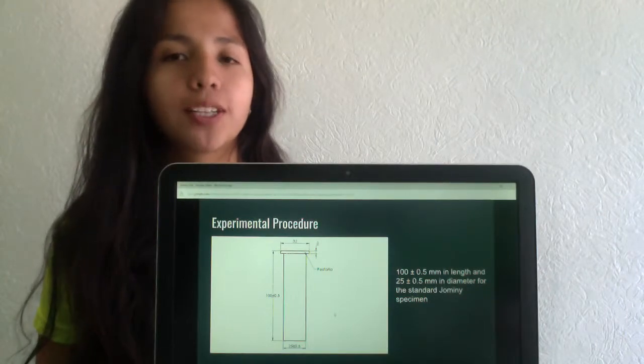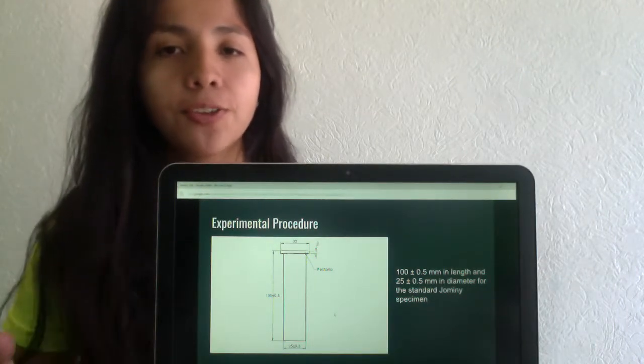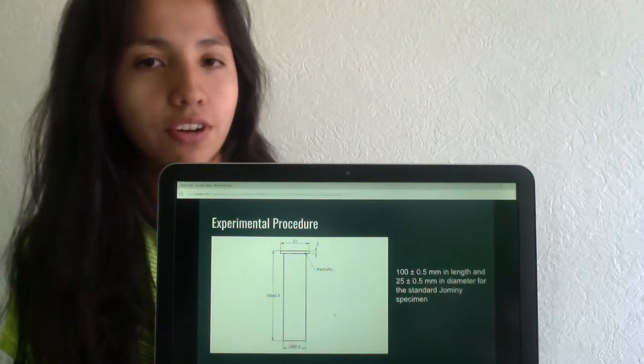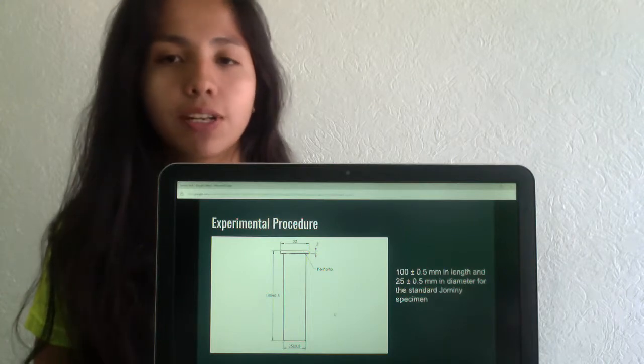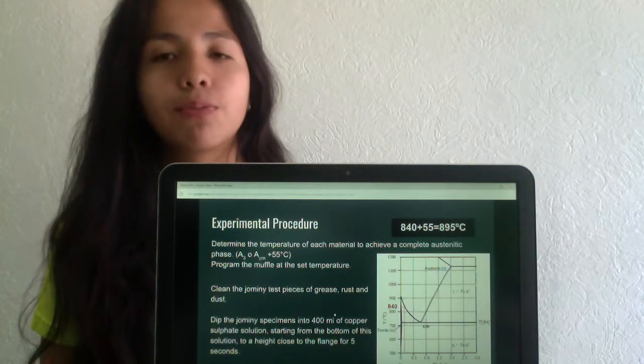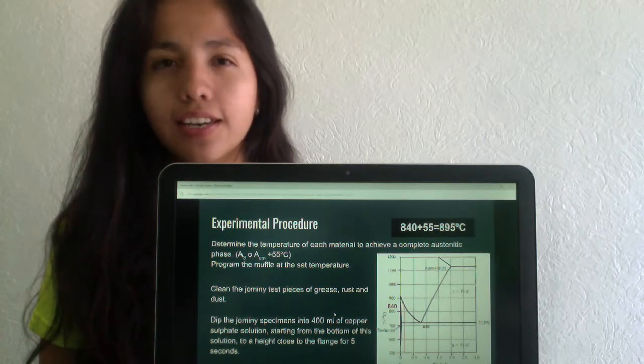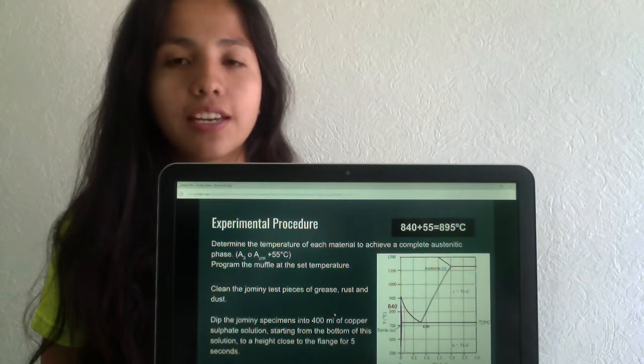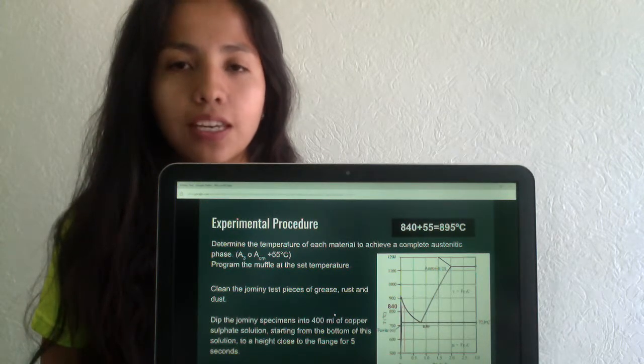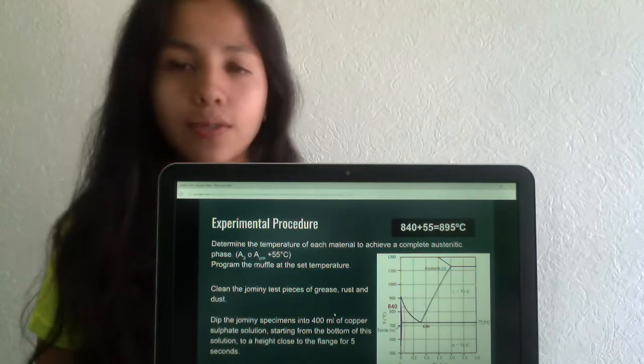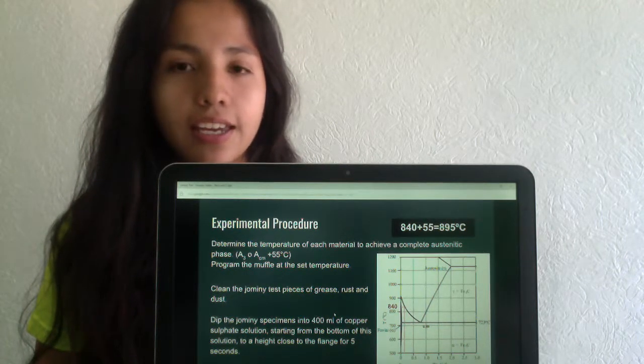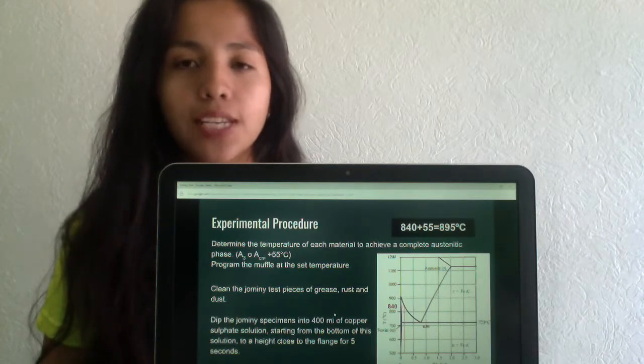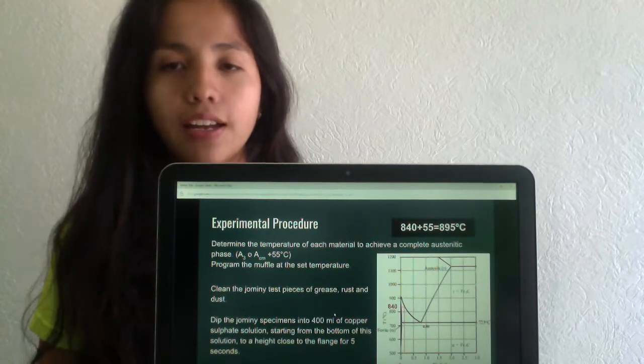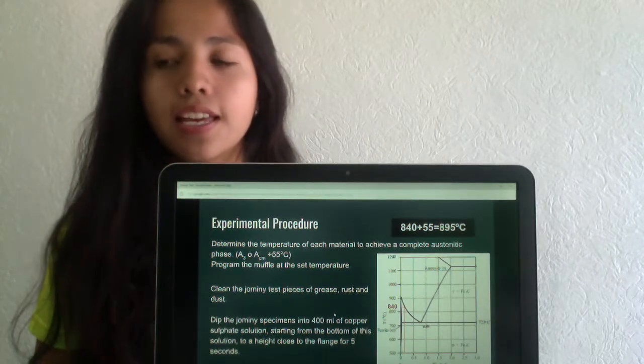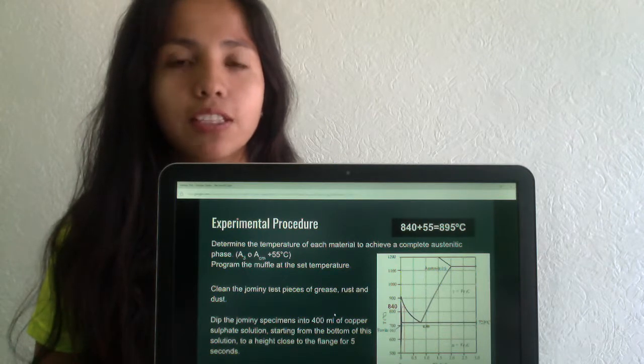For the experimental procedure of this practice, we need a specimen shown in the figure. It has a height of 100 millimeters and a diameter of 25 millimeters. Then we need to determine the temperature of the muffle. For this, the steel needs to achieve the austenite phase, and using the phase diagram, the intercept of the A3 curve, which is 840 Celsius degrees, plus 55, gives us about 900 degrees. This is the temperature that the muffle needs to be.